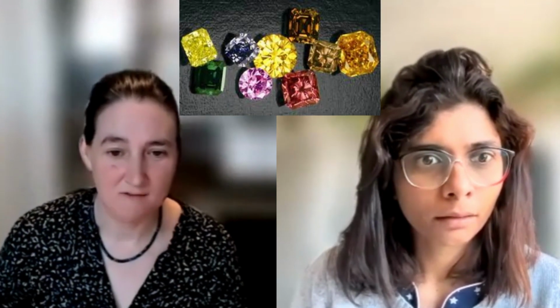So silicon looks kind of silvery anyway, but it's not a metal, right? It's a semiconductor. But if you squeeze it, it actually turns into a metal. Oh. I know, it's so cool. In the microscope, you see it go all silvery and metallic looking, and it looks a bit like mercury, and you can see it kind of ooze out a little bit, and it's turned into this metallic form of silicon. And then when we unload it, depending on how we release the pressure, we can get all these different exotic phases formed. Oh my God. I could talk to you for hours.